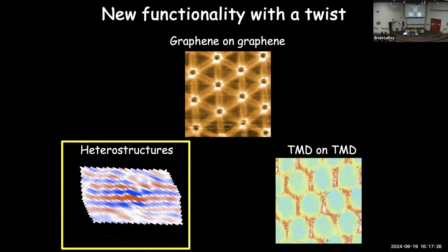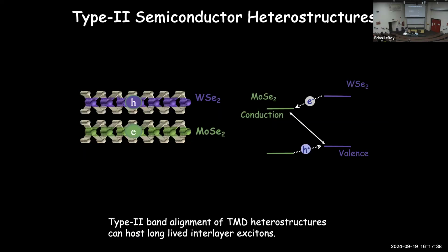All right, just a couple more minutes maybe here to talk a little bit more about the optics of when you put these materials together. As I alluded to on the last slide, if you have this combination of molybdenum selenide and tungsten selenide, you can create an electron in one layer and a hole in the other layer. The electrons are living in the conduction band of molybdenum selenide. The holes are living in the valence band of the tungsten selenide. And so that will allow you to create a long-lived exciton, a bound state of these electrons and holes. Because they're living in different materials, they can live for a long time.